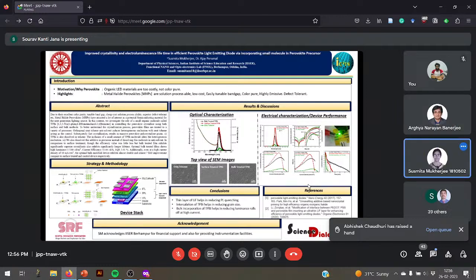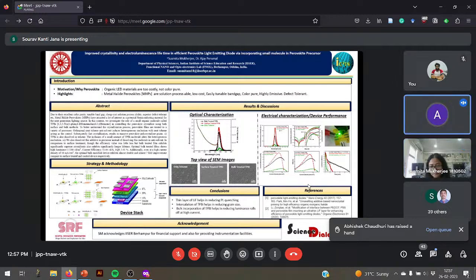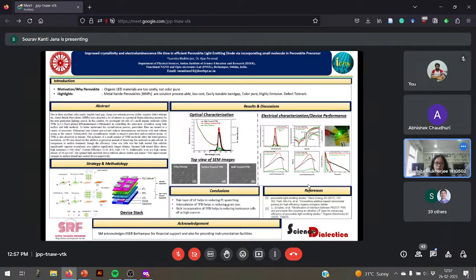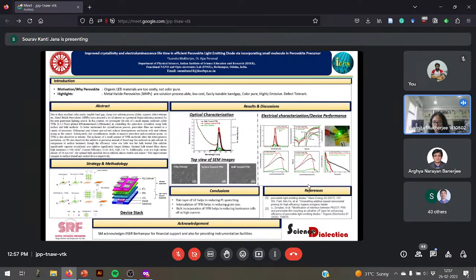Sushmita, at some point you talked about a tunable band gap. How do you do that in this system, and why is it important? Sir, with perovskite it is very easily tunable. Here I am using a green emission layer. The perovskite is an ABX3 compound, from AX and BX2, where X is a halide. If you change the halide, it has a direct connection to the band gap transition. If you use chlorine, it will be blue emitting. If you choose iodine, it will be red emitting. I am using bromine in between, so now it is green emitting. So if you change the halide, you very easily get a tunable band gap from solution processing.